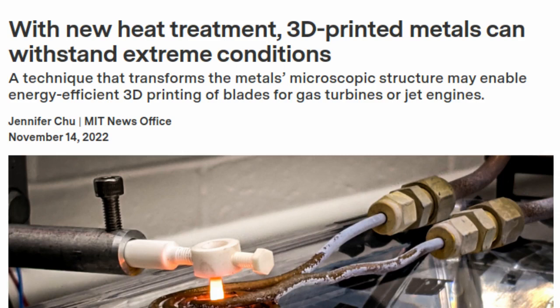But efforts to 3D print turbine blades have yet to clear a big hurdle: creep. In metallurgy, creep refers to a metal's tendency to permanently deform in the face of persistent mechanical stress and high temperatures. While researchers have explored printing turbine blades, they have found that the printing process produces fine grains on the order of tens to hundreds of microns in size, a microstructure that is especially vulnerable to creep. In practice, this would mean a gas turbine would have a shorter life or less fuel efficiency.